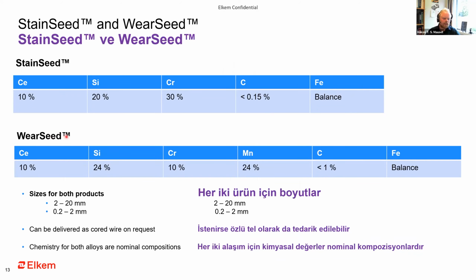The wear seed is designed for manganese steel. So here we have quite similar: 10% cerium, 24% silicon. Then we have 10% chromium, as a lot of the manganese steel contains some amount of chromium. We have 24% manganese, and then the carbon is less than 1%, which should be okay, as most of these manganese steels contain more than 1% carbon anyways. And then iron is the balance of this alloy as well.